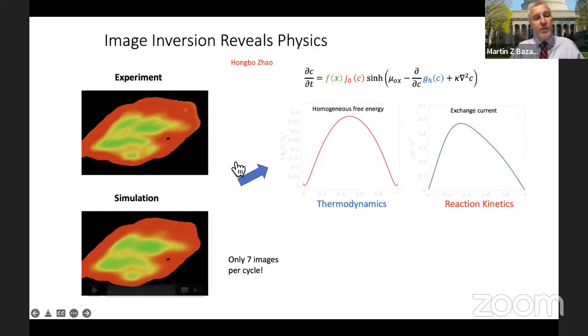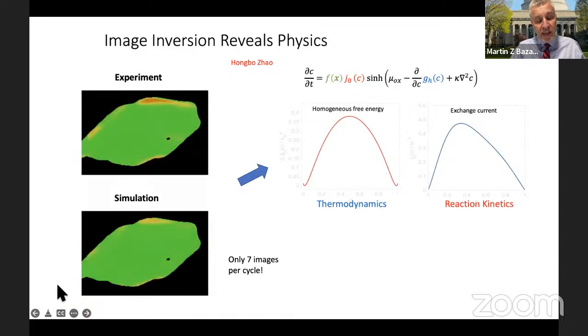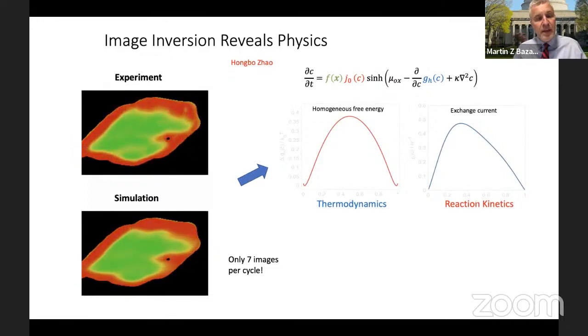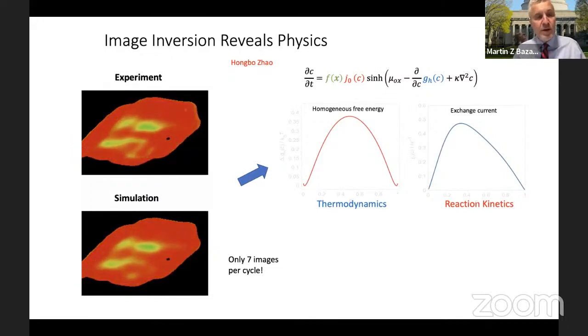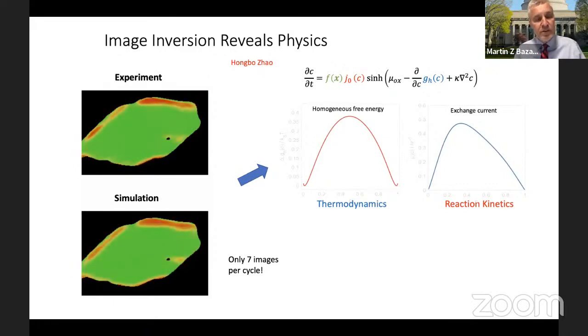Before I tell you those results, let me just show you how well for this particle, we can learn the simulation on the bottom to make it match the experiment. And this is like an actual lithium iron phosphate nanoparticle with all of its defects and everything. And essentially, it's almost impossible with the human eye to even see a difference between the simulation and the experiment. And again, we have a hole right here.